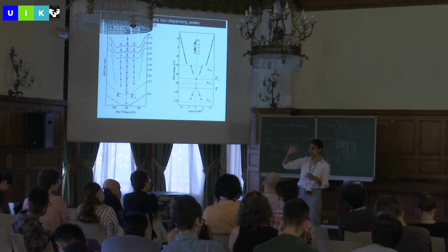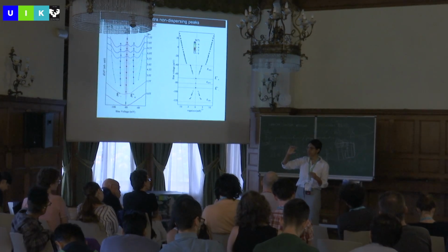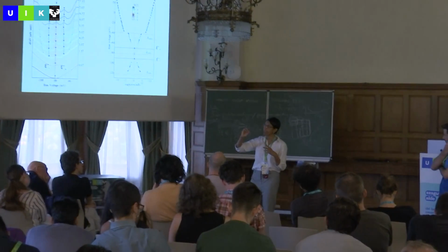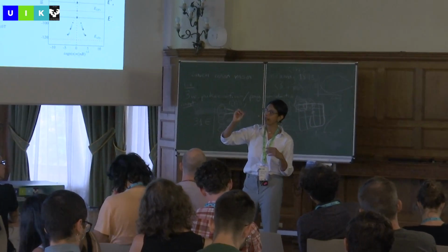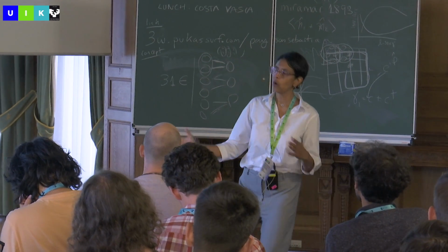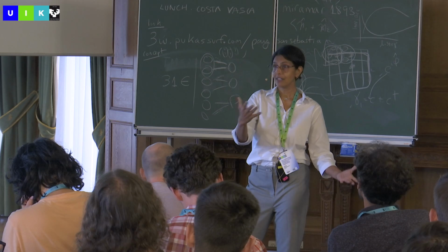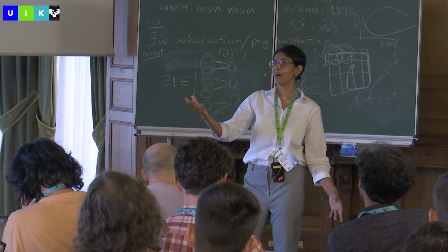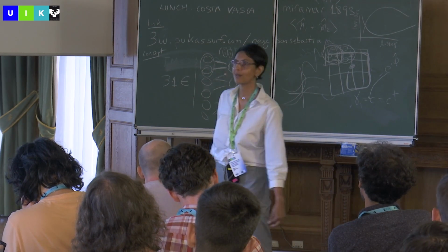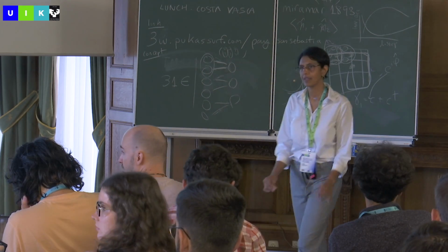The band gap is going to get smaller and smaller. The surface state continues to exist. And then there's going to be a critical point. At that critical point, the surface state is supposed to span the entire bulk. And then you go over to the trivial side, and then we still have surface states, but they're Rashba-like. That's what I'll show you tomorrow. Thanks. Yeah.